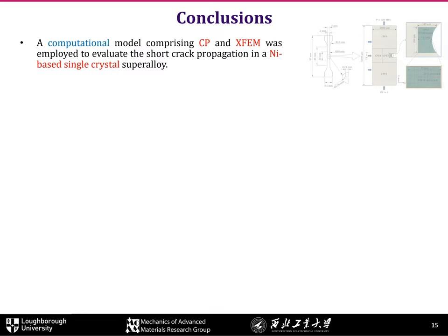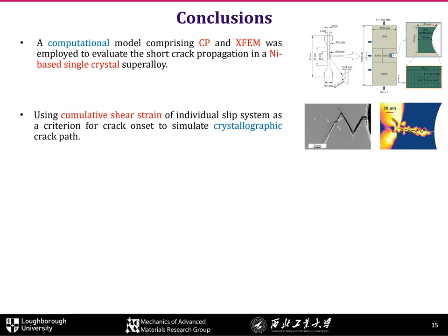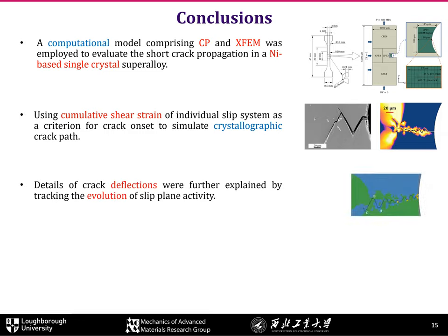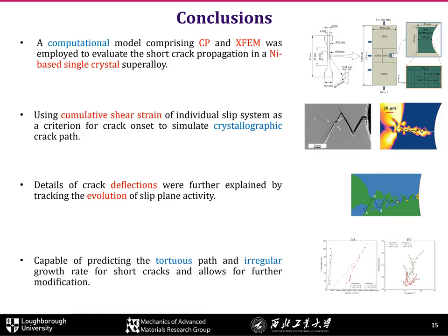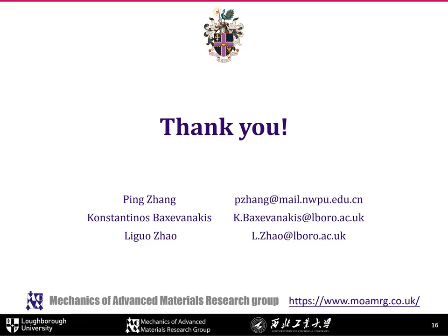Let me summarize the presentation. A computational model combining crystal plasticity and XFEM was employed to evaluate short crack propagation in a nickel-base single crystal superalloy. The cumulative shear strain of individual slip systems was used as a criterion for crack onset to simulate the crystallographic crack path. Details of crack deflections were further explained by tracking the evolution of slip plane activity. The model is capable of predicting the tortuous path and irregular growth rate for short cracks and allows for further modification. Thank you for listening.